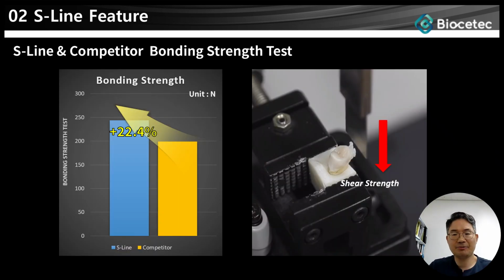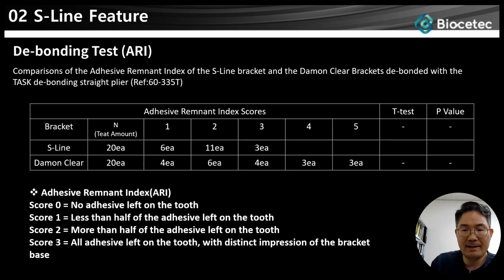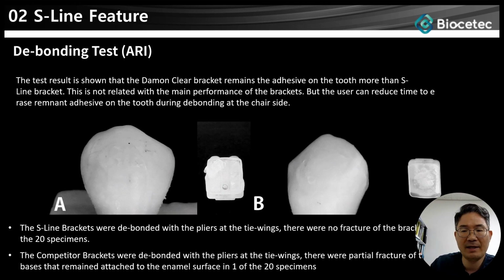So the bonding strength was performed using ISO 11405 standard test. S-line has 22% higher bonding strength than other product like this. And the ARI score means the Adhesive Remnant Index, which indicates that the lower the value, the better bonding strength of the bracket. The S-line ARI score shows the lower value compared to the other bracket, which shows the reliable bonding strength. And we also check the fracture after debonding process. In case of S-line, there was no fracture in 20 specimens, but the Damon Clear had one bracket fracture of 20 specimens.